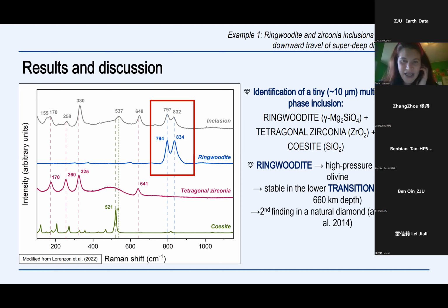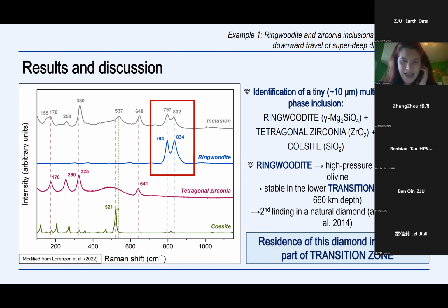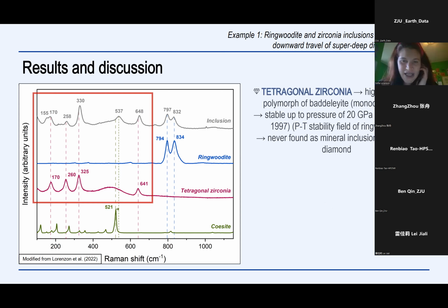So, what does the finding of ringwoodite tell us? If we have a ringwoodite inclusion within our diamond, this means that at some point in its history in the Earth's mantle, our diamond resided in the lower part of the transition zone, where ringwoodite is stable. Continuing with tetragonal zirconia, this mineral phase is the high-pressure polymorph of baddeleyite, which is zirconium oxide. Its presence is in line with the presence of ringwoodite because this mineral phase can be stable at depths up to 20 GPa. The finding was also important because this was the first time that a natural tetragonal zirconia was found in a natural sample, in this case an inclusion within a diamond.